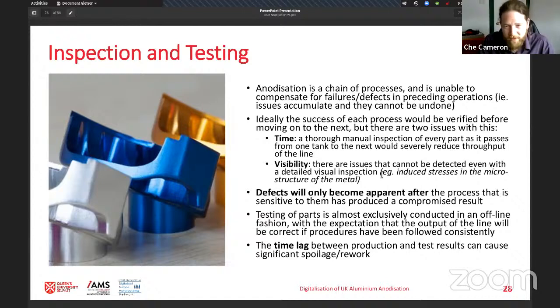And even if you did want to take that time, there are issues that just cannot be spotted, like those micro stresses. You can't see them through inspection. The anodization shows them. So the defects become apparent after the process is done, which, if you have relatively fast inspection, isn't an issue. But for instance, corrosion testing in a salt spray chamber or other longer tests or off-site tests, there can be quite a large time lag between when the anodization production was done and when the test results came back, which can result in a lot of spoilage or rework if it turns out that the line has been producing bad batches for several days.